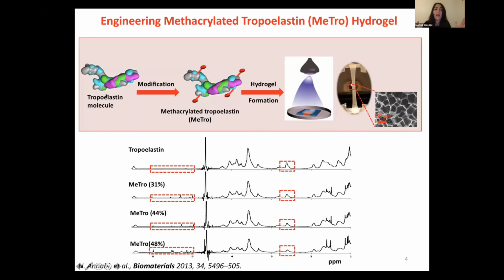Tropoelastin has lots of great properties. It has many lysine residues in one tropoelastin molecule. So when we expose it to cells, it can interact with different cells and help regeneration. So we use tropoelastin molecules and we modify them with a one-step reaction. Through methacrylation, we form methacryloyl tropoelastin, it's short for MeTro, that has this functional group on the polymer chain. So once we expose it to light, and if we add a photoinitiator, it can cross-link within a few seconds to form a highly elastic biomaterial.